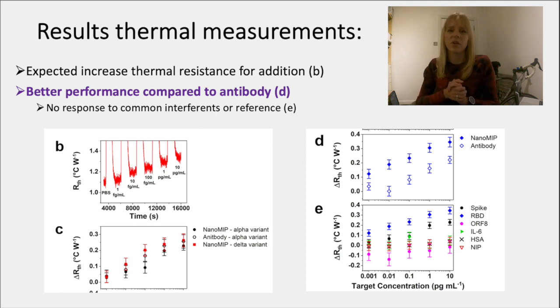So in essence, if you've got a reference material, you will add something to the solution. You see this little spike because you add in a cold liquid, but nothing really changes in the signal. Whereas if we are working with COVID-19 or samples that are spiked with COVID-19, we would see a gradual increase. So gradually you would see the signal going up. And we can use this to construct a calibration curve and actually determine how much it would go up if we have a known amount of antigen.